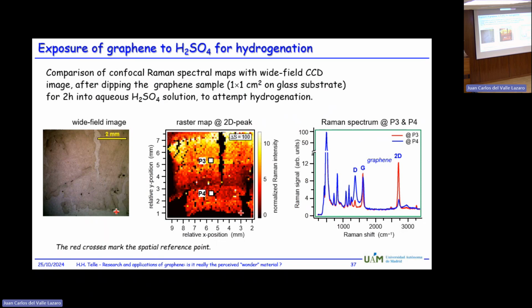That was in 21. And as you can see, we were not experts yet, because partially we destroyed the sample in the process because you touch it with your hands. And if you remember, graphene is a single layer system, so less than a nanometer. So clearly, if you touch it, boom, it goes. But nevertheless, we were able then to do Raman microscopy on that and have a distribution.